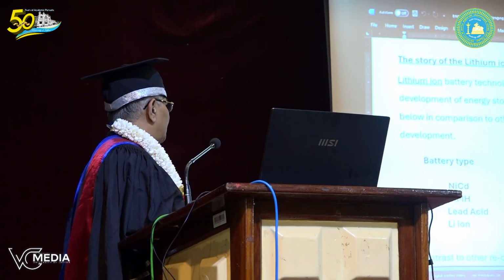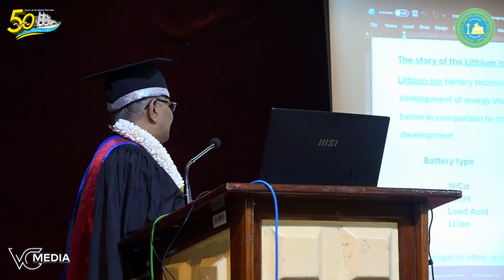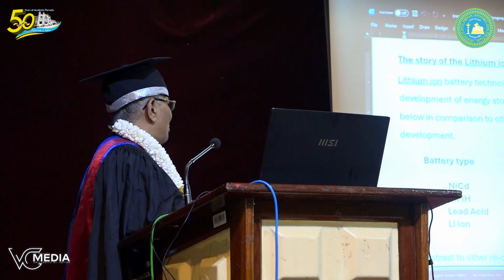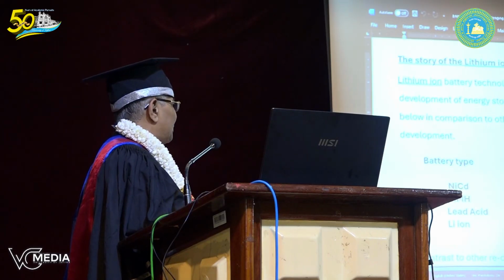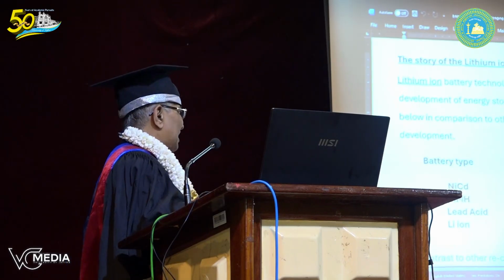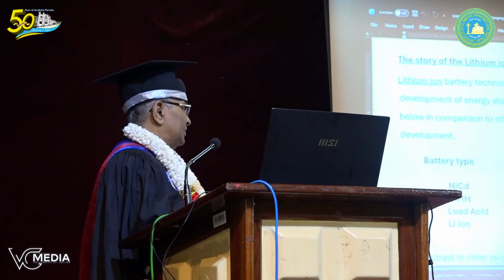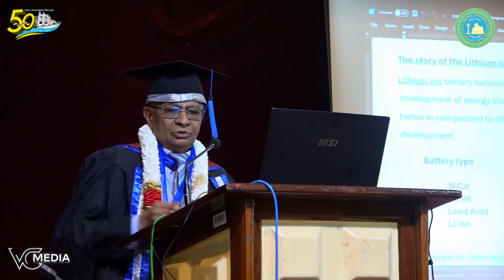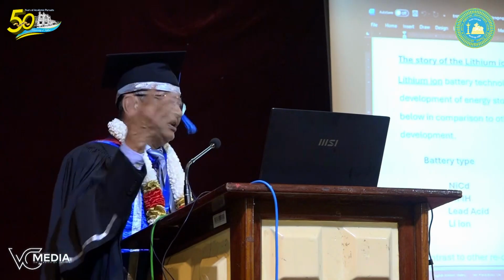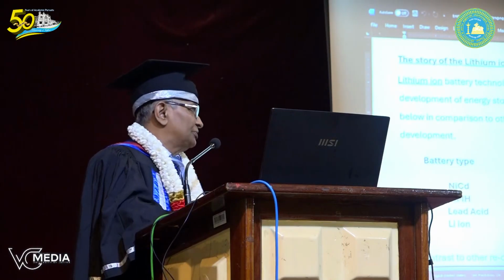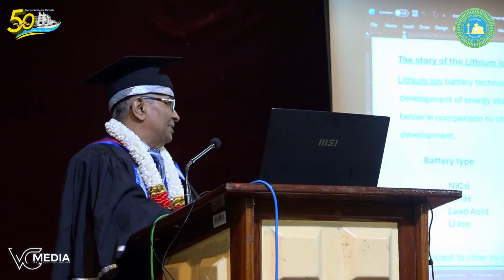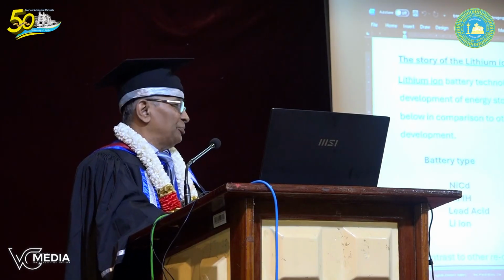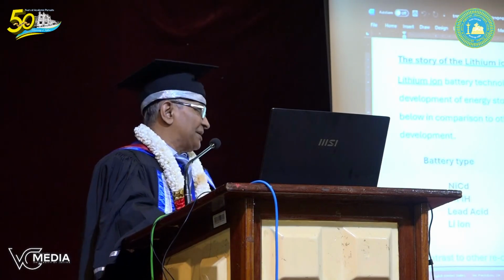Compared with these, lithium-ion has a voltage of 3.7, an energy density of about 250 watt-hours per kilogram, and a cycle life of over 3000. So it's used everywhere: in laptops, mobile phones, drones, and mobile electronic equipment, you name it, the lithium battery is there.